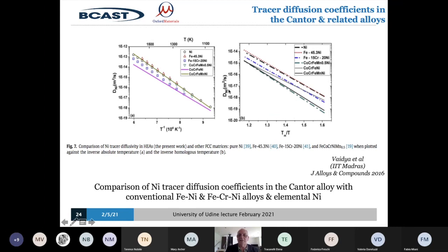This shows the speed at which nickel atoms move in the Cantor alloy, which is at the bottom, actually 2 Cantor alloys, the original one and the modified one, and in some comparison face-centered cubic materials like pure nickel and a nickel superalloy. And you can see that the speed at which the atoms move at any given temperature is about an order of magnitude slower. So the atoms move more slowly.